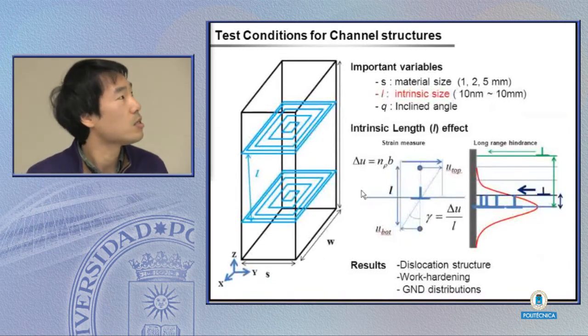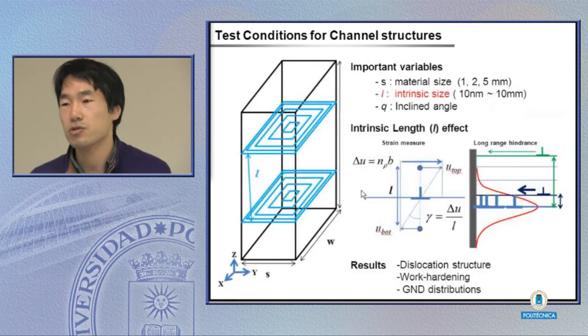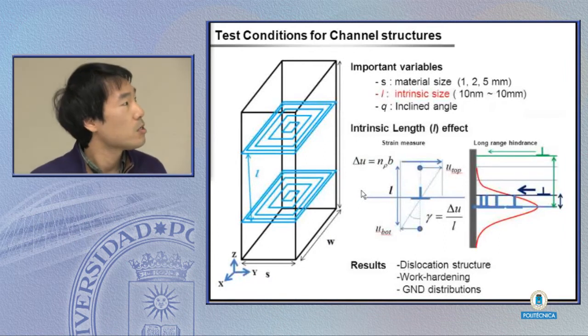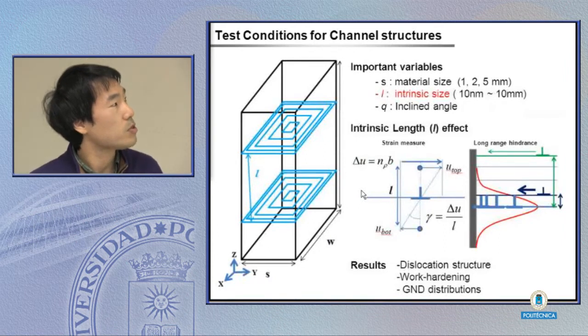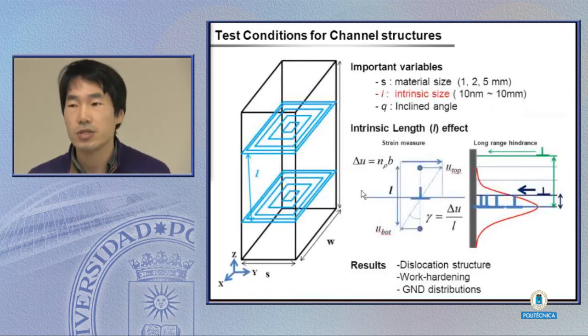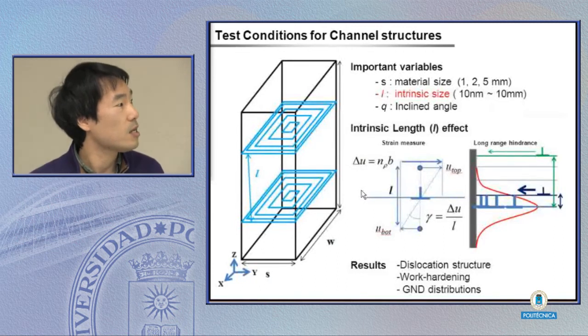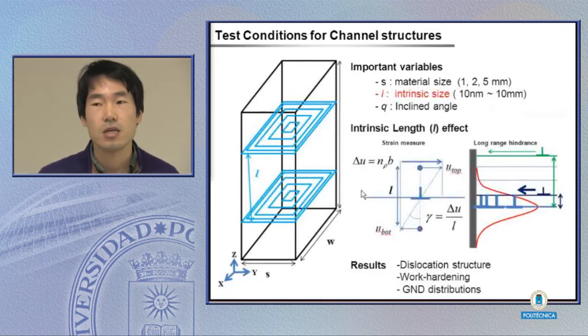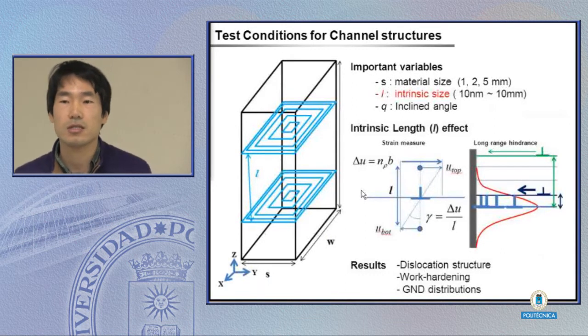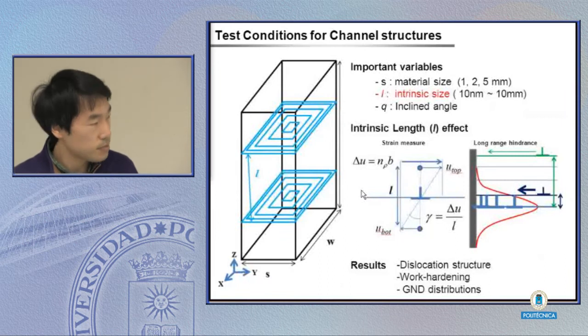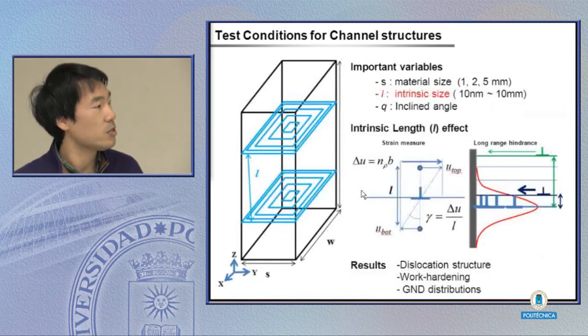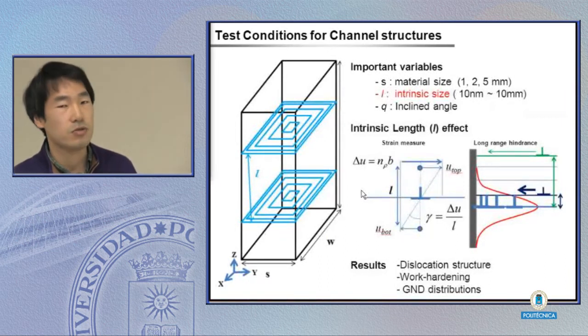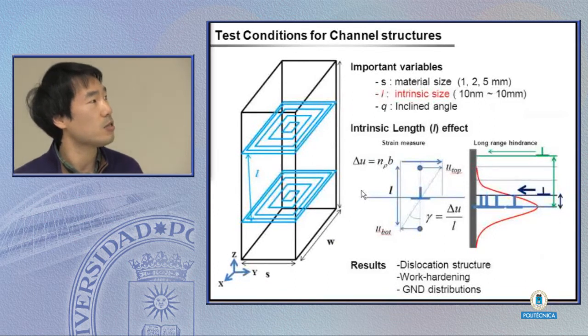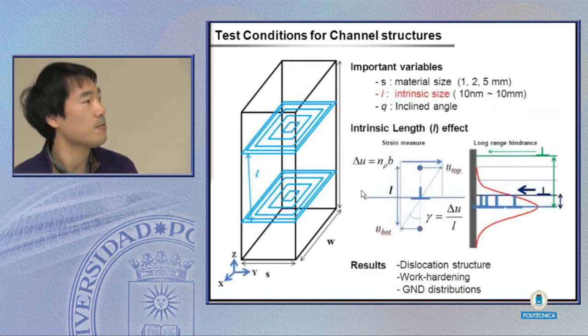And this is the test condition to see a size effect. The dislocation is evolved at each slip plane inside the isolated crystal. Here we have the two different sizes. One is the size of the channel, which is the width, which represents the material size, and the other is the distance between slip planes, which represents the intrinsic size.